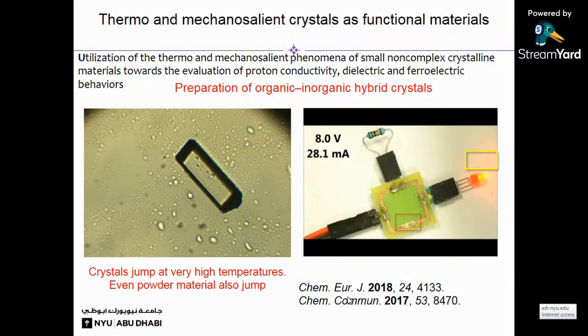So you can see on the left side, these are simple thermosalient crystals. When you irradiate them, they jump. But when we coat these thermosalient crystals with some kind of conductive coating, in this case we have coated with silver paste, we can create some kind of electrical fuses. What happens is, when electricity passes, heat is also dissipated. So due to this heat generated during the current flow, the crystals are able to change from one form to another form due to the phase transition temperature. So as I said earlier, we coated with silver paste. When the current passes, they jump.